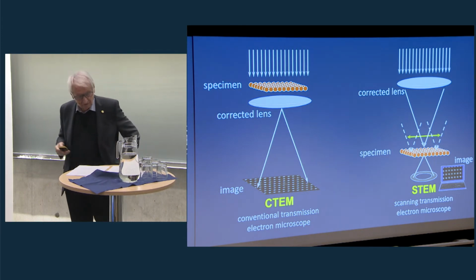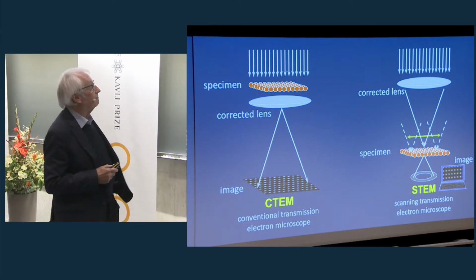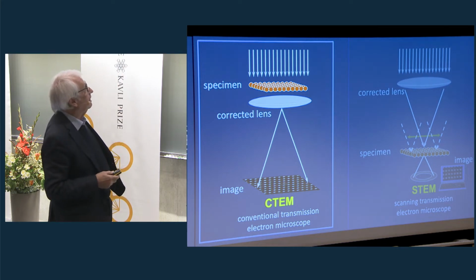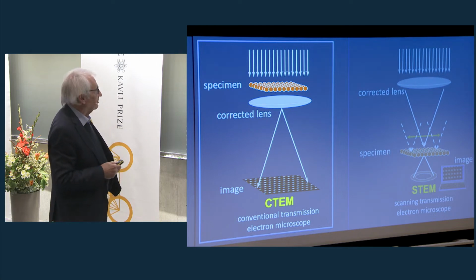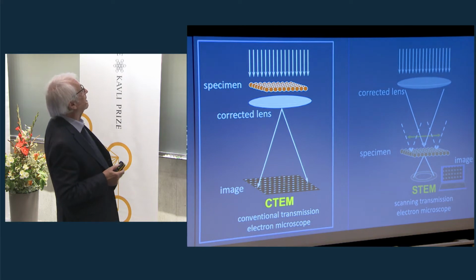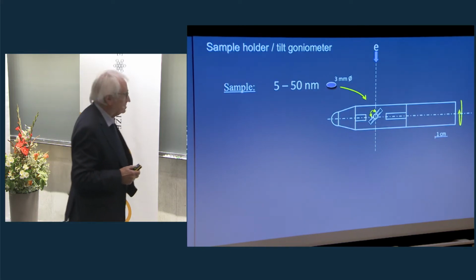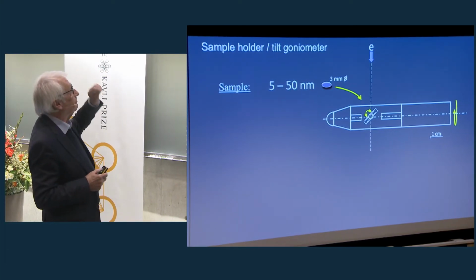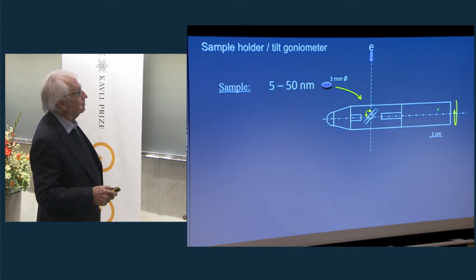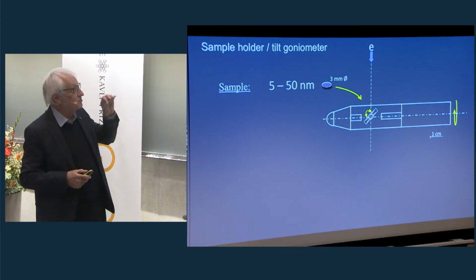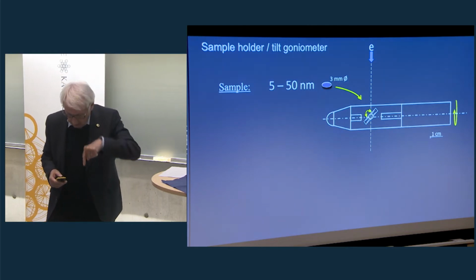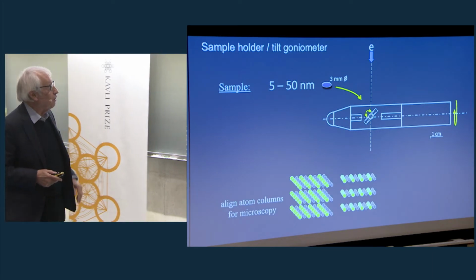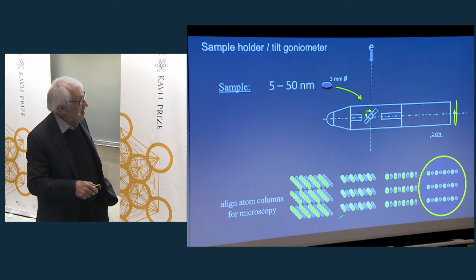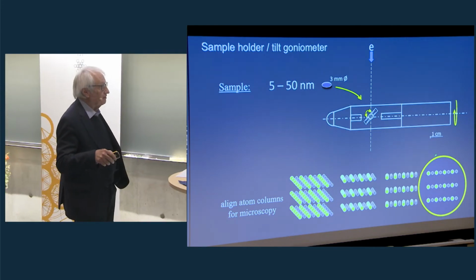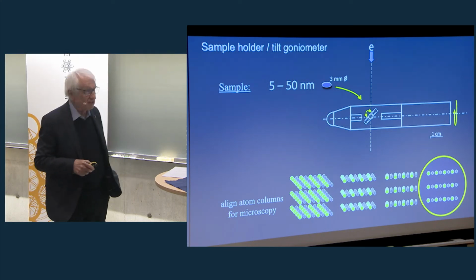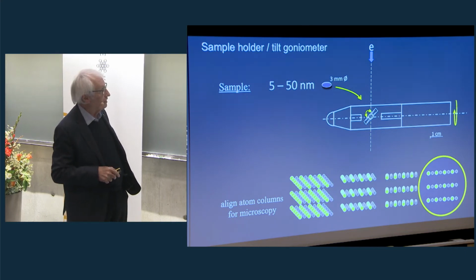Now, when we have the microscope, we have, of course, to have samples fitting into the microscope. I will only talk, by the way, about conventional and aberration-corrected transmission electron microscopy, and leave the rest to the next speaker. So we have samples which are extremely thin, about 5 to 50 nanometers in thickness, and we mount these into tilt goniometers. That means we can align the samples in such a way that the atomic rows are going along the viewing direction, which I have sketched here. That means when we look at these images later on, we have in most cases other atoms behind the particular atomic sites.